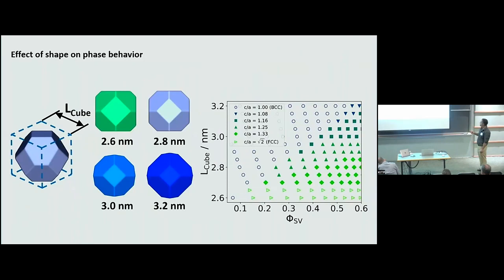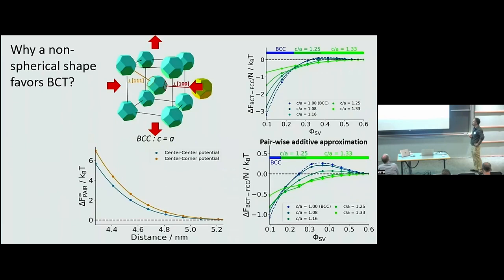I think it's fair to look at this diagram. Again, we have the amount of solvent, and now in this axis, there is a parameter that controls the shape of the particle. And right now, you see there are a lot of points in this phase diagram that correspond to BCT. So we believe that this really is an explanation of why BCT is stabilized. We tried to understand this a little bit better. Sometimes it's difficult with this kind of model to understand the reason, because all the information is there, but you need to find a way to extract it. In this case, we looked at the pair potential between nanoparticles, which is an approximation that may work, may not work. But in this case, we checked and it did work rather well.